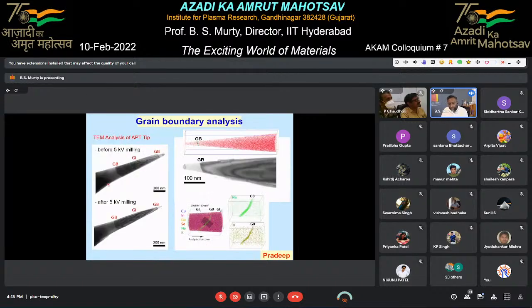You can even see what kind of atoms are sitting at the grain boundary. This is one such example where you can see some elements such as sodium and potassium going to the grain boundary. You can detect them very easily. The grain boundary thickness is of the order of 1 to 2 nanometers, and it is possible to see what elements are settled there and what the composition of that grain boundary is.